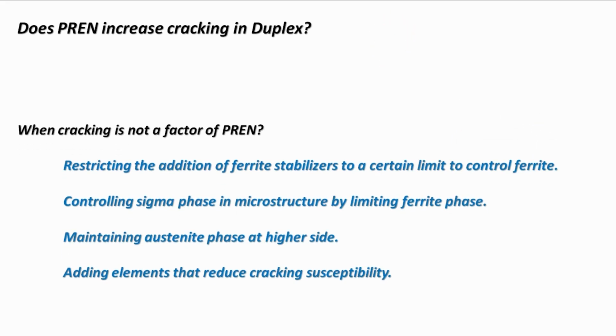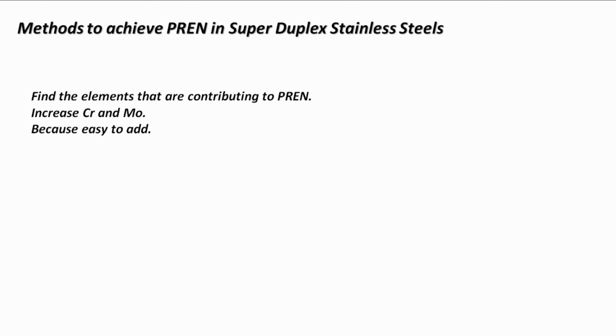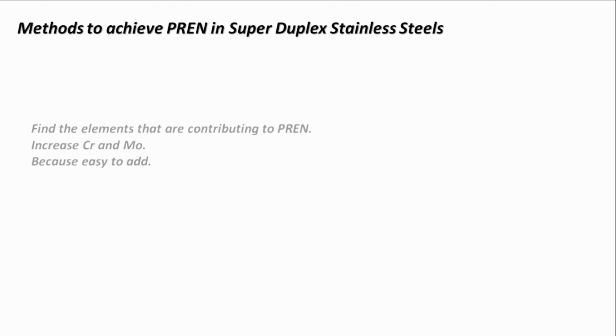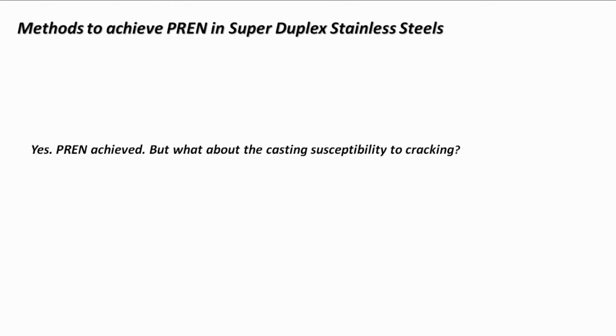PREN is not really a problem when we restrict the addition of ferrite stabilizers, keeping them limited to control the ferrite. So controlling the ferrite controls the sigma, and drastically, the brittleness of the material also we can reduce. As methods to achieve PREN, first we think about addition of chrome and moly because it is easy to add. Yes, it is a good idea, PREN is achieved, but the susceptibility to cracking increases.